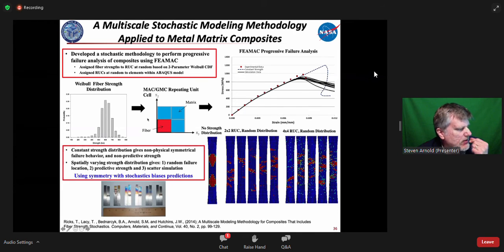But when we took into account the statistical variation of the fiber, in that we spatially varied the strengths of the fiber, we are able not only to hit the value, or predict the value, of the overall failure of the coupon, but the location of the failure was also able to be predicted quite nicely. And the lesson learned out of this was, when you start taking into account distributions, clearly you need to be careful and not impose symmetry boundary conditions or whatever, because that would bias your predictions significantly.